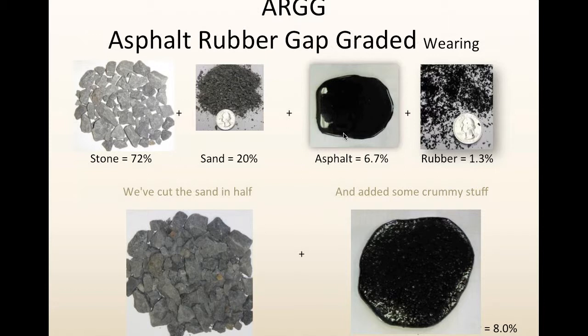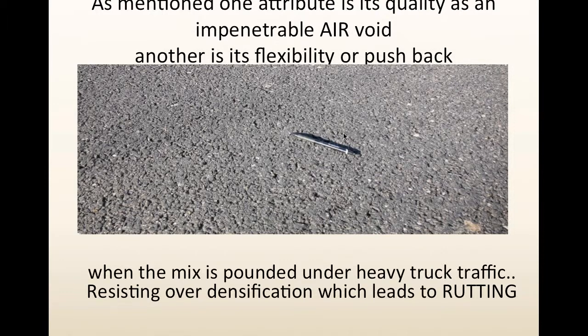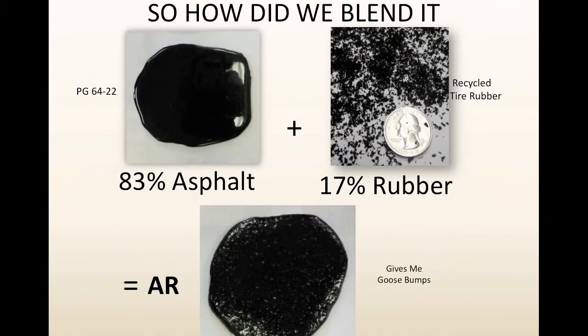All right, in the asphalt rubber gap graded wearing course that we're looking at, you can see the components here. The sand's been cut in half, so you can see it's about a 72-20 blend of stone and sand, and then the asphalt at basically not quite an 80-20 blend. You're looking at 6.7% liquid and 1.3% rubber blended together. As I mentioned, one of the other attributes of rubber is that it's an impenetrable air void. Its flexibility also allows it to push back, which when it's pounded by heavy truck traffic resists over-densification, or what ends up in rutting and flushing in our pavements. I'm sure you've seen rutting and flushing if you've driven anywhere in the United States.